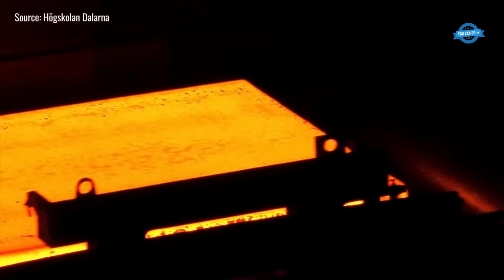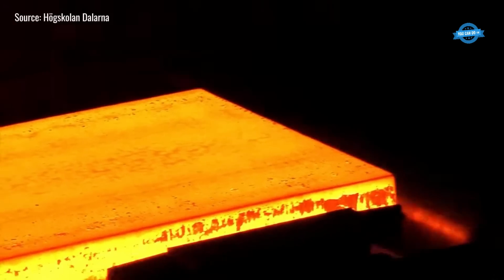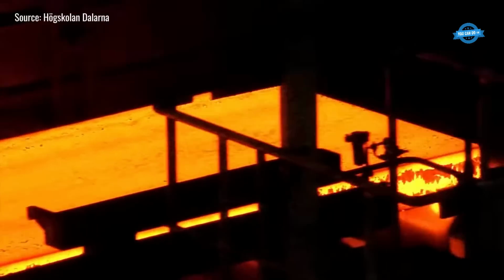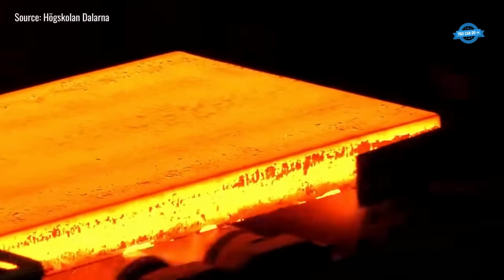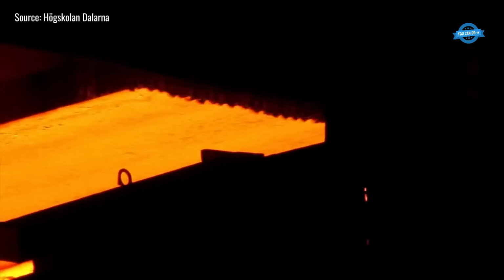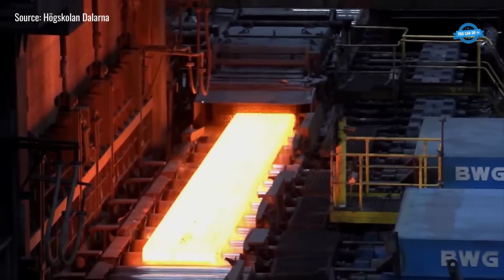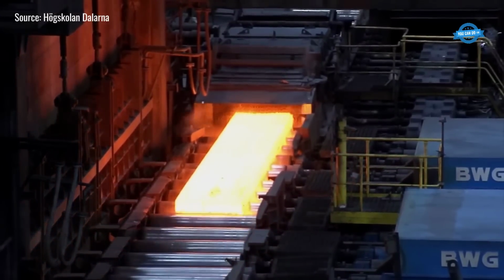During this stage, the material reacts with oxygen in the air, forming an oxide layer known as mill scale consisting of oxide formed on the surface. If the oxide layer remains on the material during rolling, it risks being rolled into the steel material, adversely affecting the surface quality of the final product. This layer must be removed before rolling to prevent defects. High-pressure water jets, spray the surface to cleanse it before rolling.